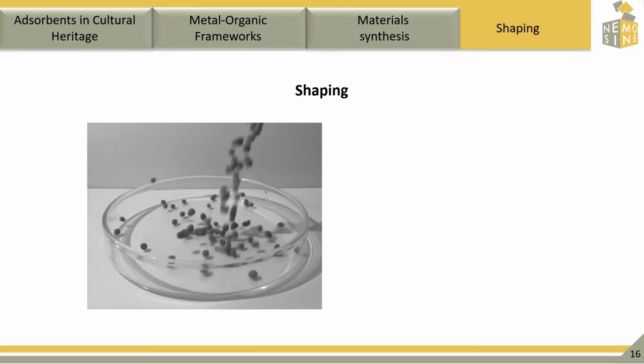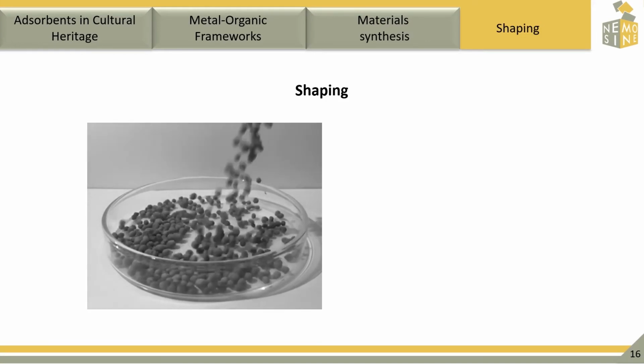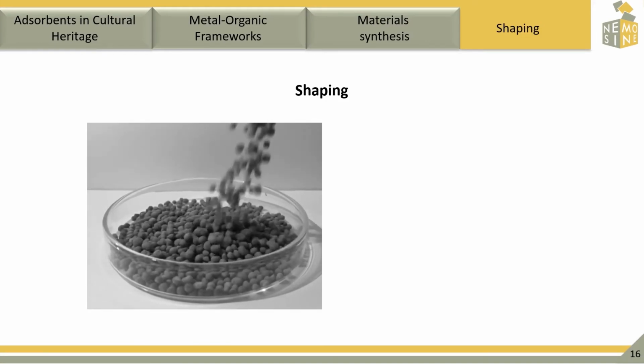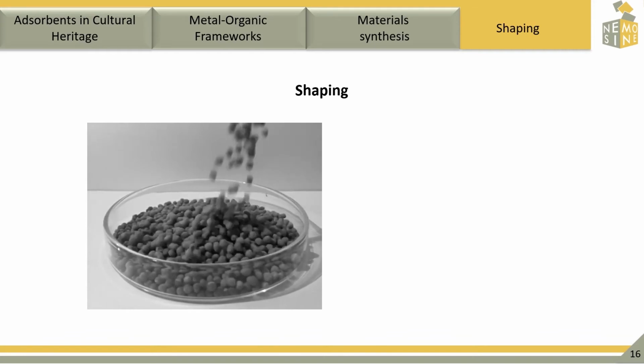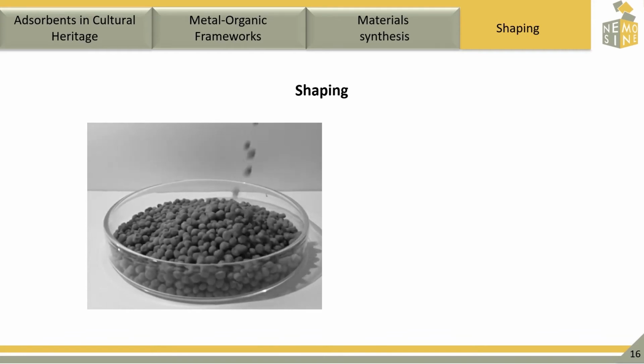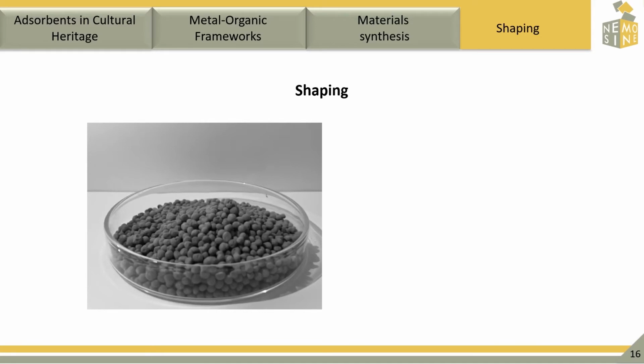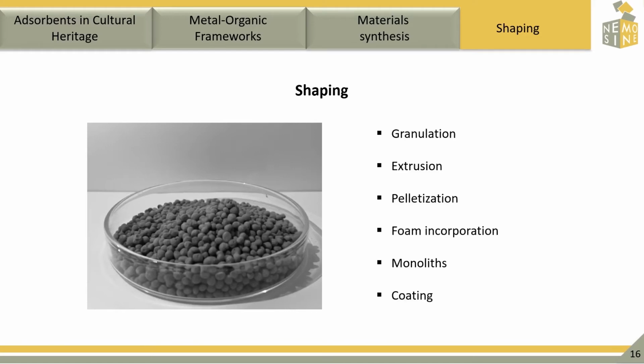Shaping is also something that should be done with MOFs in order to have something that is stable, that doesn't release powder, since this is impractical, and also leads to the loss of valuable material and can also contaminate sensitive materials, which is our case in the case of films. Thus, this can worsen the degradation state. Different methods of shaping can be explored. Usually the choice of shaping process is based on the form that needs to be obtained in order to have a more adequate product for the final application.